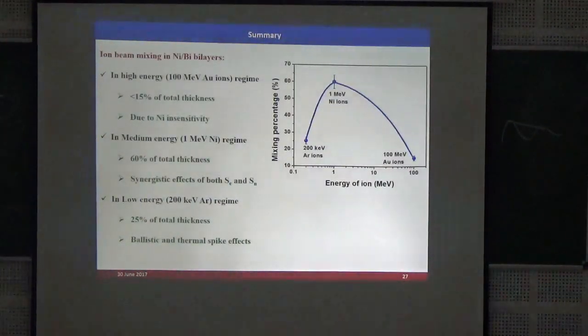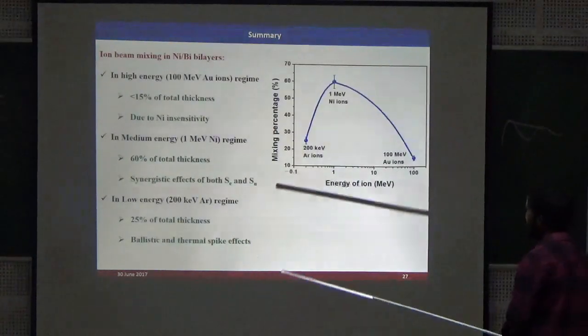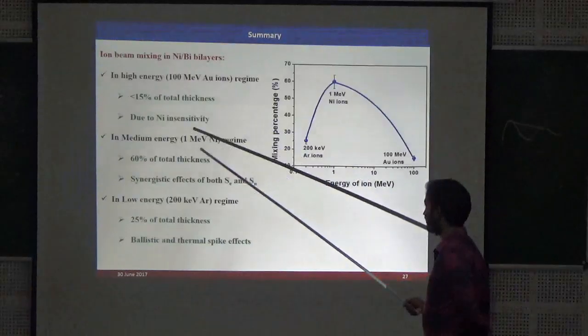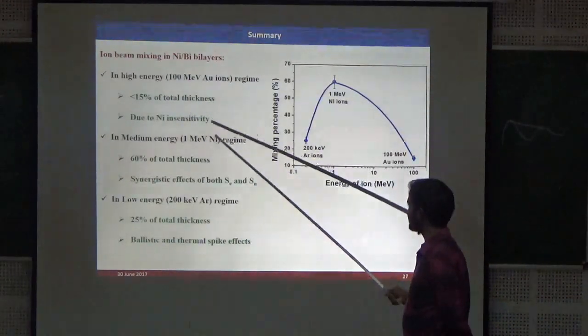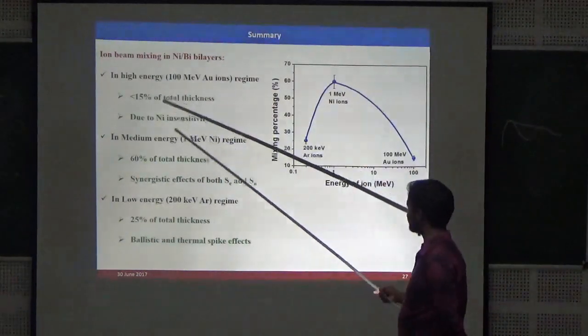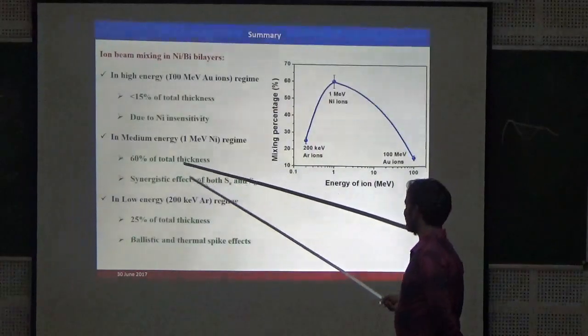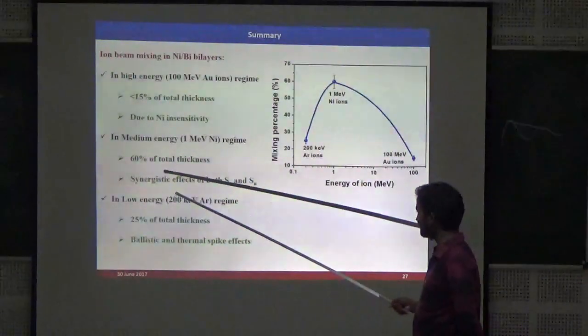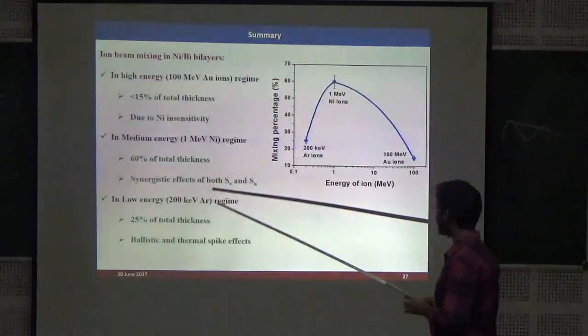So here is the summary. We have studied ion mixing using three different energy regimes. In the high energy regime, we have seen less than 15% of the total thickness. It was attributed to limited mixing due to nickel insensitivity. In the case of medium energy, we have seen almost 60% mixing enhancement in the total thickness. That was attributed to the synergistic effects of both Se and Sn.